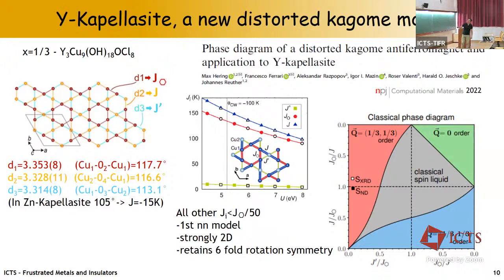Yttrium-kapellasite is predicted, so that's where it should lie, with two different structures, but okay, I won't go into the detail. It should be around here. So it should be in this one-third long-range order phase, which I will describe further. And so there's a phase that is symmetrical here, and here that's a more trivial phase when frustration is suppressed, basically.